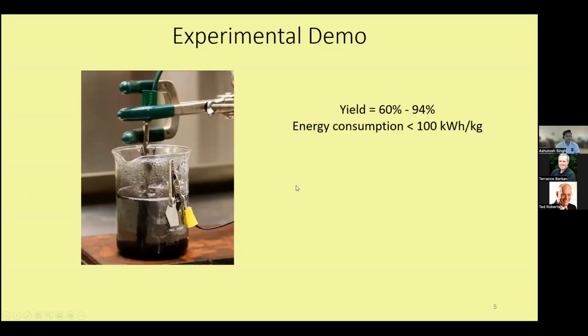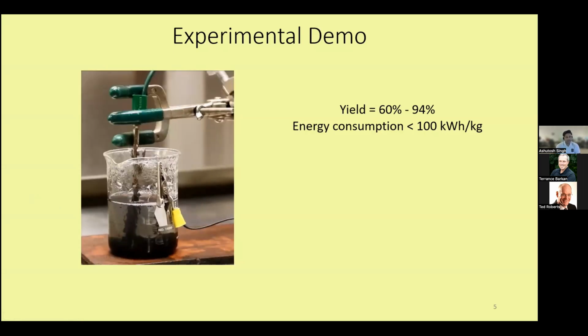In all the chemistry that we work on and have worked on in the past, we observed a yield in the range of 60% to 94% with varying degrees of quality. The highest yield, for the chemistry that we have IP around, is 94%. Our total energy consumption is less than 100 kilowatt hours per kilogram of graphene produced.